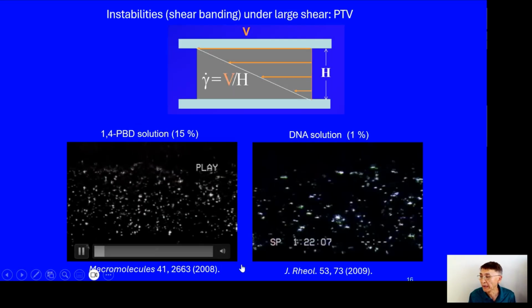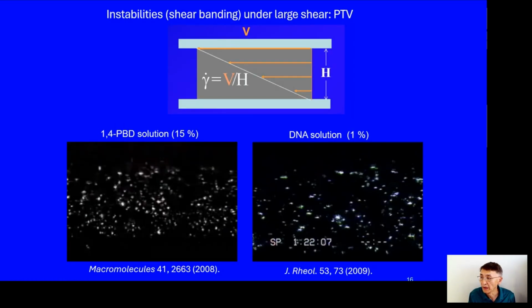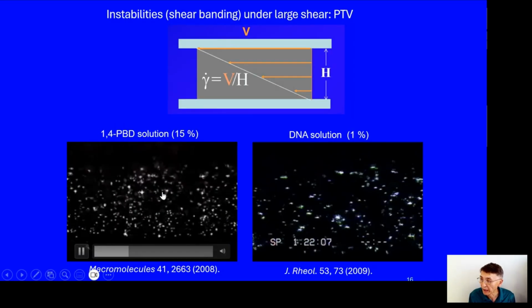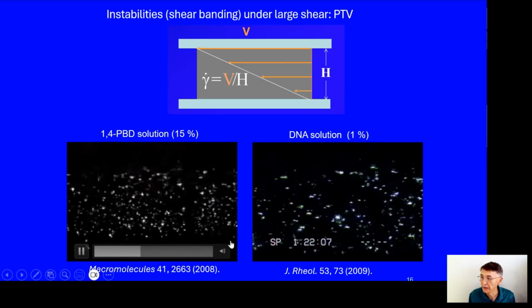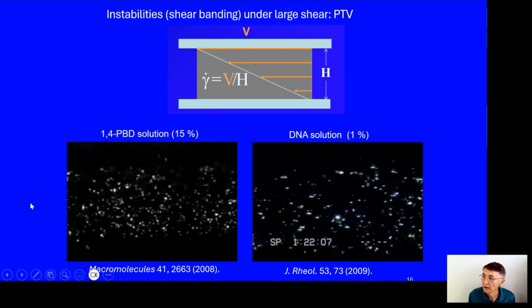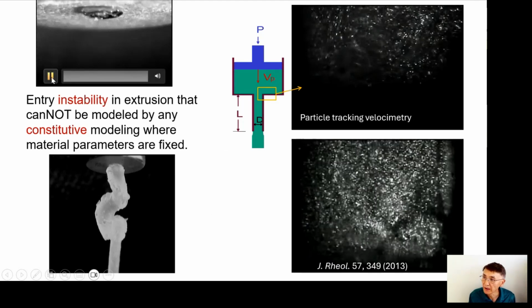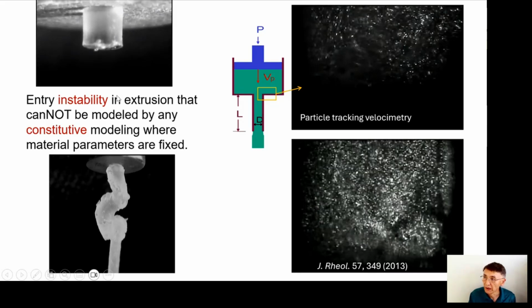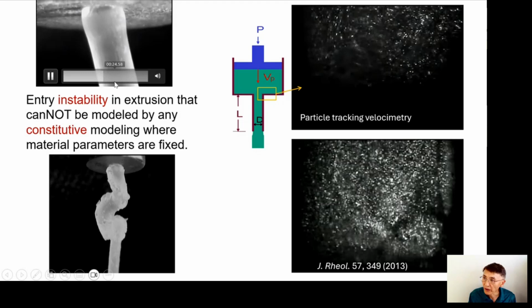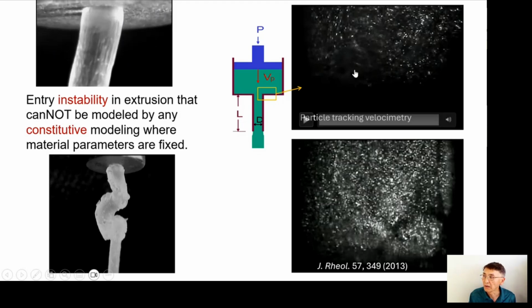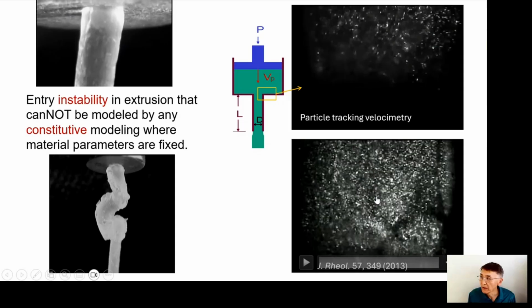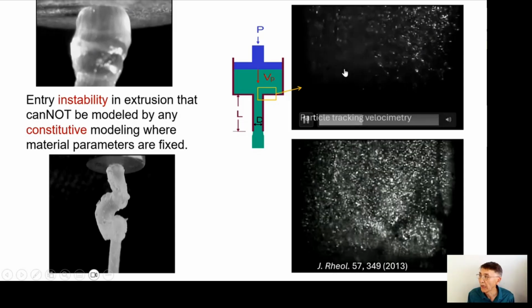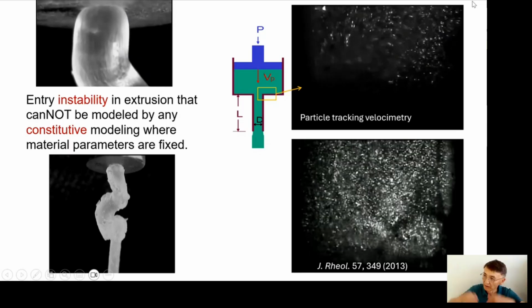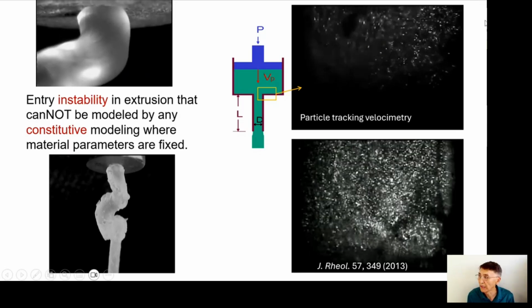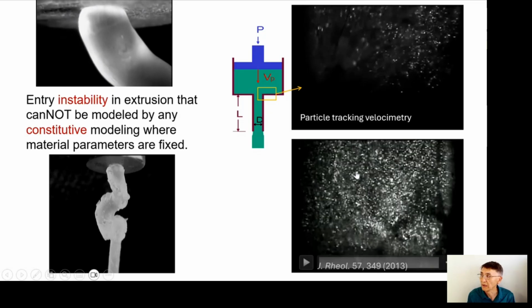And this is one of the movies by now. It's close to 20 years old, showing that this innocent flow-like behavior is not so innocent. You see, it breaks as if it was a piece of solid. So it's uneven deformation. And this uneven deformation carries all the way through during processing. So for example, this movie was showing extrusion, but when you try to extrude very fast, at the end, you find your extrudate is distorted. And we know exactly how this occurs by looking at what happens as the polymer rushes to converge into the die at the entry. They suffer this solid-like failure.